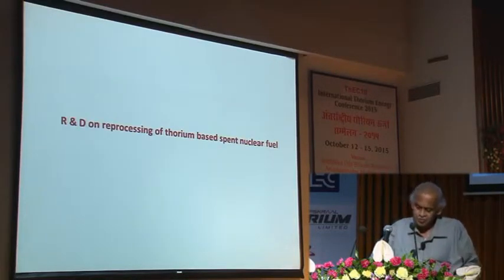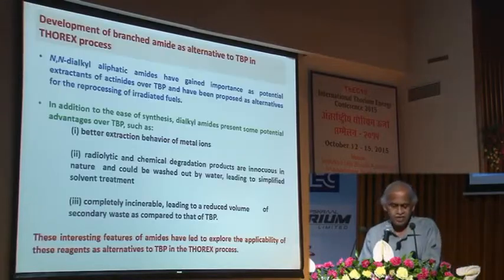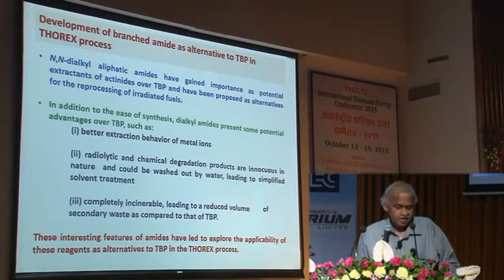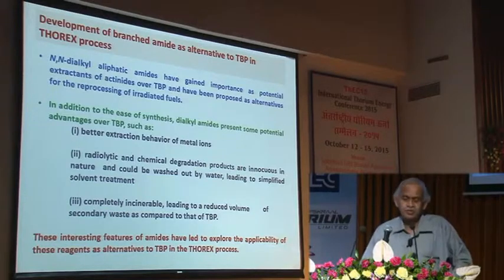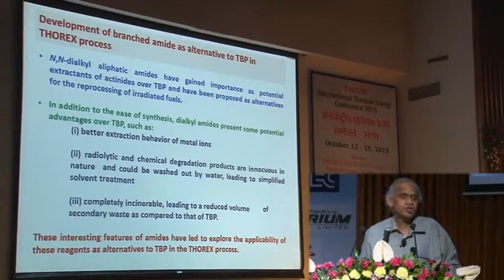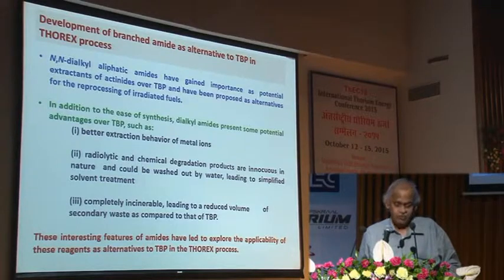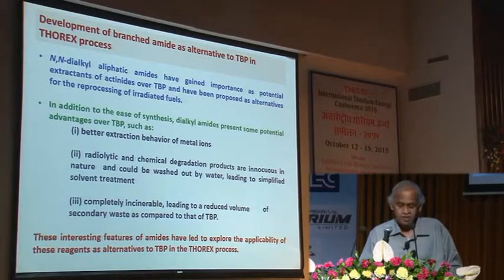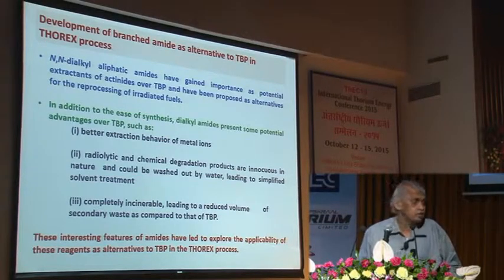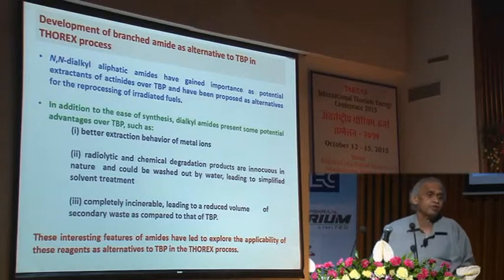I just come to the reprocessing of thorium-based spent nuclear fuel. This is a very small contribution from our group. Of course, Vattal's group has been actively pursuing this activity. We were able to show that amides, branched amides, have the potential to be an alternative to TBP in the THOREX process. Particularly the dialkyl aliphatic amides have better extraction behavior for metal ions. Radiolytic and chemical degradation products are innocuous because they could be washed out by water, leading to simplified solvent treatment, and they are completely incinerable, leading to reduced volume of secondary waste as compared to that of TBP.